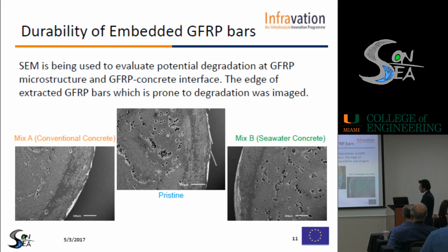So we take a picture at actually the edge of the bar, which was in contact with the concrete, and that's actually the most important area, because it's very prone to all the damages. Whatever is going to happen is going to start from the edge. So if you take a picture from the edge, and nothing happened at the edge, you are pretty sure that nothing is going on in the middle of the bar. So that's why we took a picture at the edge, and again, as you see, this is mix A, this is mix B, no degradation, right?